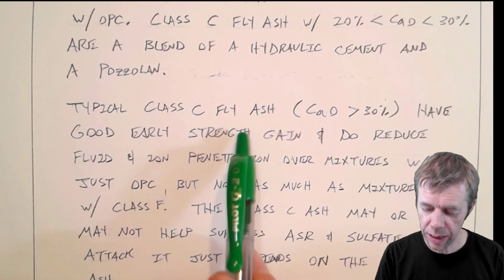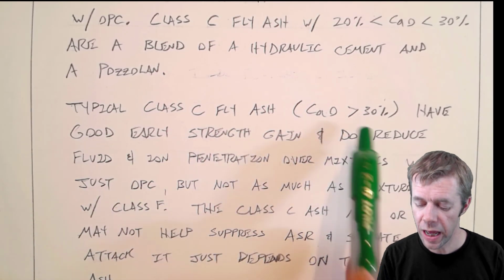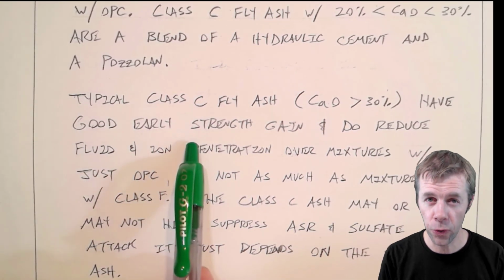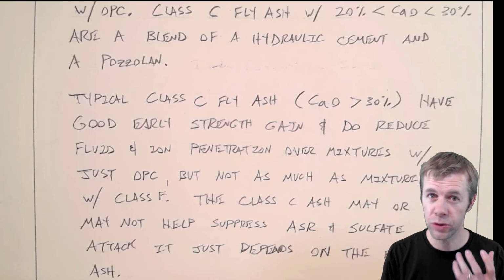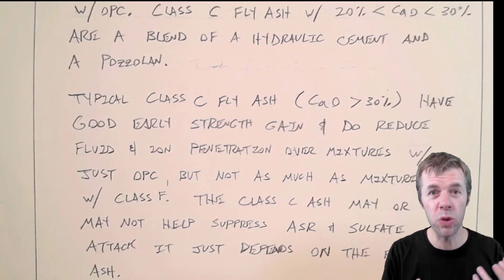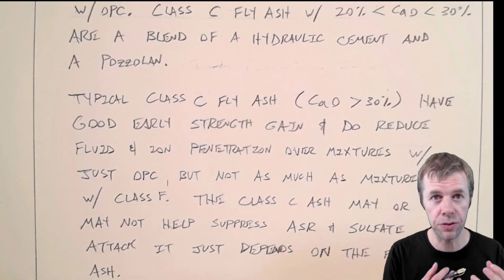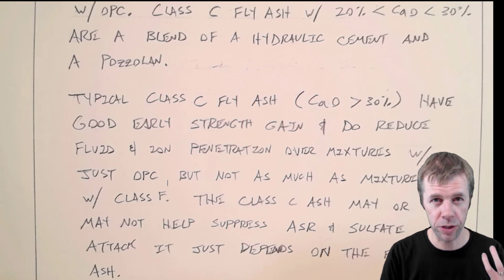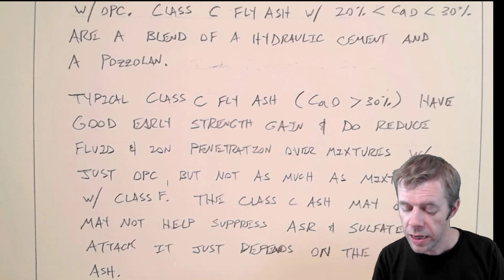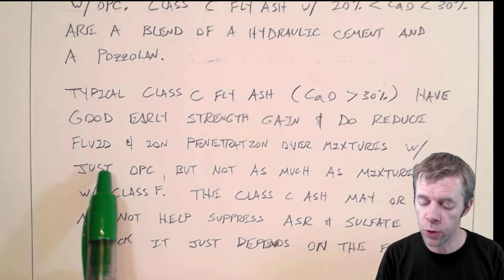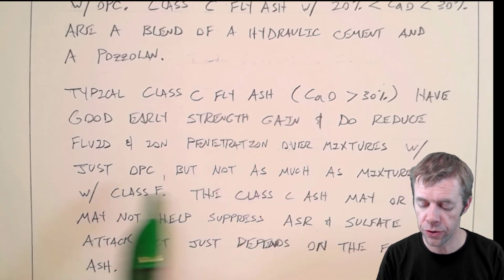Typical Class C ashes, those are the ones greater than 30%, have really good early strength gain. Pretty much the same as Portland cement. You really don't notice much difference between a 100% Portland cement mixture and one of these mixtures with a Class C fly ash. Now, they also reduce your fluid and ion penetration over mixtures with just OPC.